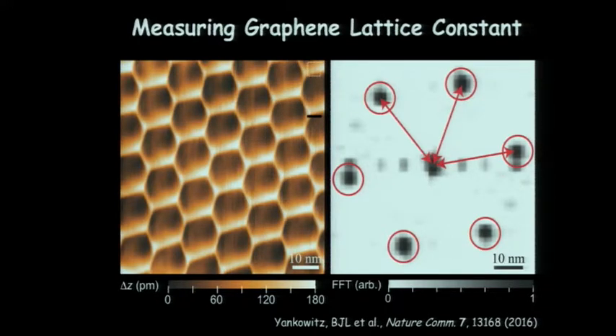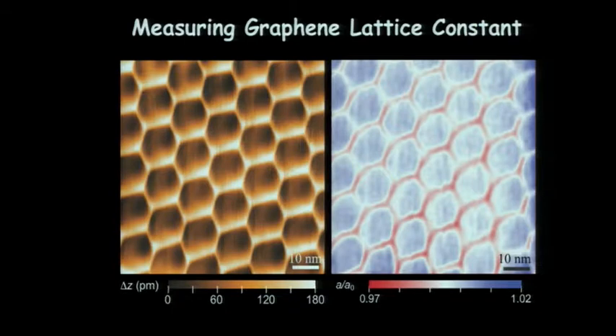For each point that the box is, we get one number, which is the length of the lattice. And then we plot that number for every position in space. So for the box here, we got a length of the lattice here. We do the same thing everywhere in the sample. And we're measuring here the measured lattice A relative to the sort of unperturbed graphene lattice. What you'll see is that there's definitely variations here. There's some parts which are smaller, 0.97. There's some parts which are longer for the graphene lattice. So there's a spatial variation in the graphene lattice.